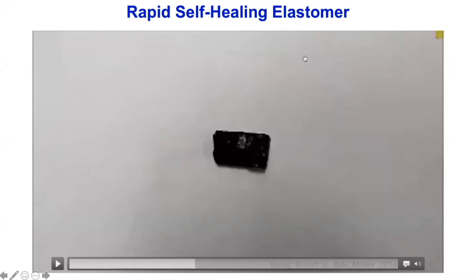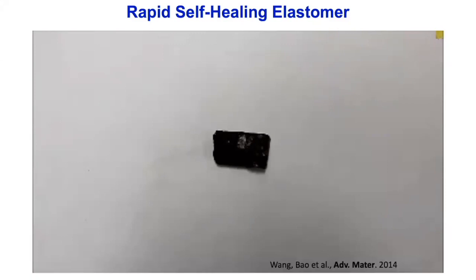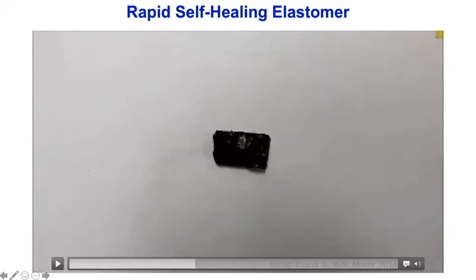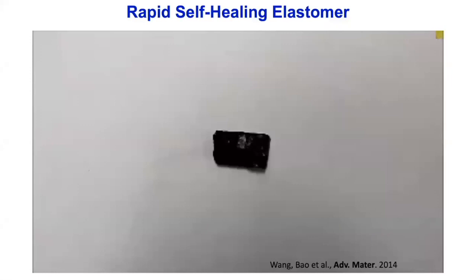This is showing an example of the dynamic elastomer that we have made, where if you cut the material and put it back together, when you cause a fracture in the material, the non-covalent dynamic bonding I just mentioned earlier, they have a weaker bonding strength and they can break first. And then when you put the two pieces of materials together, then these chemical bonds can be formed readily at